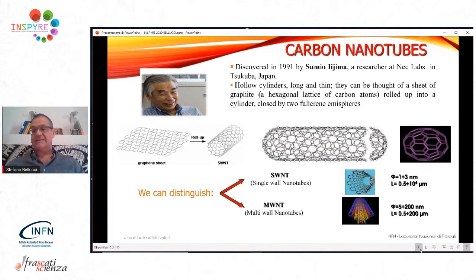More or less, the features are similar in the sense that the long and thin single-wall nanotubes have a higher aspect ratio. The aspect ratio is simply the ratio of the length over the diameter of the object. So in this case, we're talking about, I don't know, typically 10 to the 3, 10 to the 4 micron divided by 1 or 2 nanometers. So we're talking about 10 to the 6, 10 to the 7 aspect ratio. So it's very, very high, 1 million or 10 million value for the aspect ratio. For the multi-wall it is a little bit smaller because the multi-wall are thicker. They range between 5 and 200 nanometers, and the length can reach up to, even nowadays, a millimeter or a fraction of a millimeter.